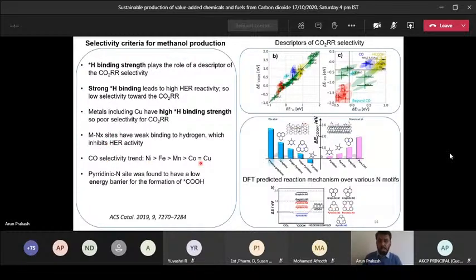So the CO2 selectivity trend for different metals: nickel is the best, then iron, manganese, and cobalt. All of them will only be equal to copper. And pyridinic site. If you have a nitrogen site, it can be of different types like pyridinic nitrogen, pyrrolic nitrogen, and quaternary, depending on the number of rings in the benzene ring to which the nitrogen is attached. If it is attached to a 6-membered ring, it is called pyridinic. If it is 5-membered, it is pyrrolic. So depending on the number of rings in which it is attached, you can determine the pyridinic or pyrrolic nitrogen. Depending on that, selectivity may change.